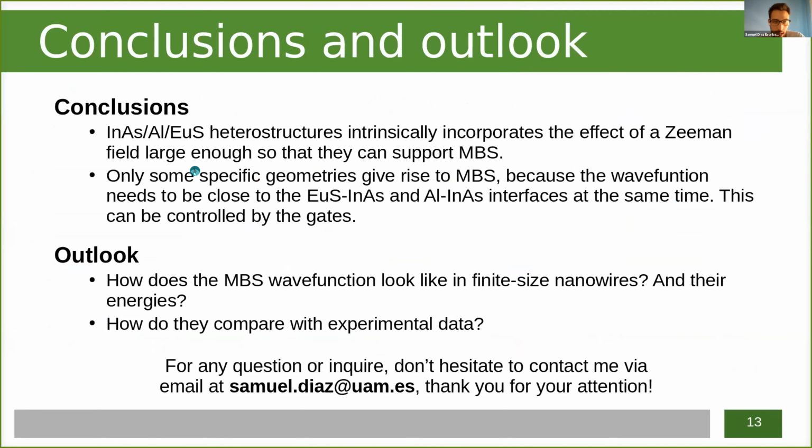So to conclude, I have shown you that these kind of heterostructures, indium arsenide aluminum europium sulfide heterostructures, can intrinsically incorporate the effect of a Zeeman field, which could be large enough to support Majorana bound states. However, due to the interplay between the position of the wave function and the interfaces with the europium sulfide and the aluminum, only some specific geometries give rise to Majorana bound states. Fortunately, this can be controlled by tuning the gate potentials.